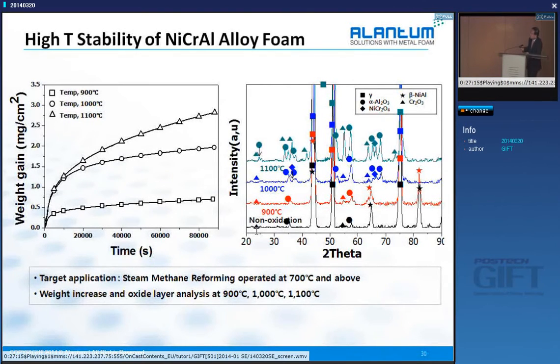Depending on the temperature, from 900 up to 1100, our gain is about 3 milligrams per square centimeter. It looks fairly high, but our competitors' gain is about 9. So that means ours is only one third of our competitors'. That's the reason why we have some benefit or advantages.